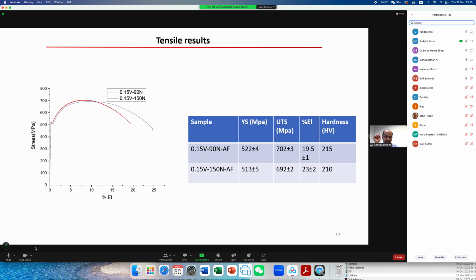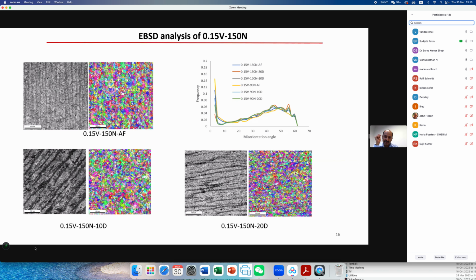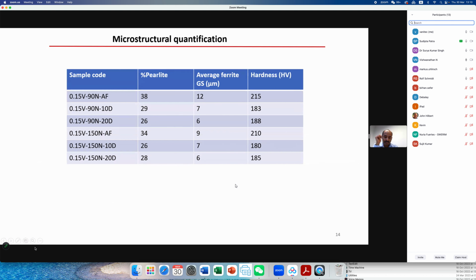Dave, just on your question, yes, it was surprising for us as well that we were not seeing any strength improvement in the higher nitrogen one, despite having a lower grain size in the higher nitrogen. The average grain size was about 3 microns lower, but still we were not noticing any strength improvement. So possibly it is something to do with the precipitation, and as very rightly pointed out by Debalai as well, it may have something to do with the amount of dissolution of vanadium nitrides, or co-precipitation, or heterogeneous precipitation on the existing interfaces. So we need to do a detailed study on that. I'll be interested to hear what your conclusions are in the next meeting.